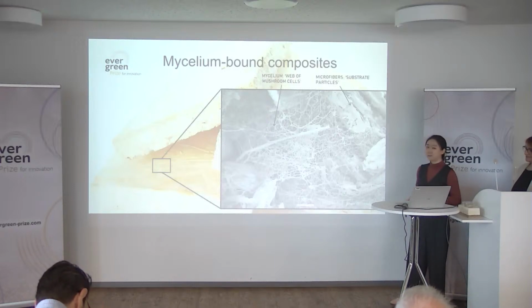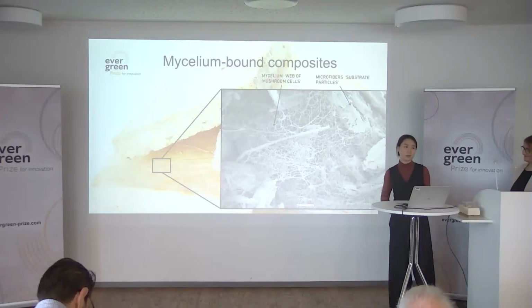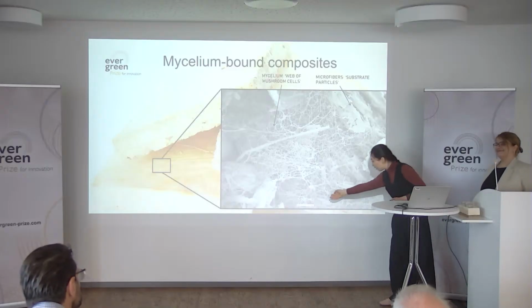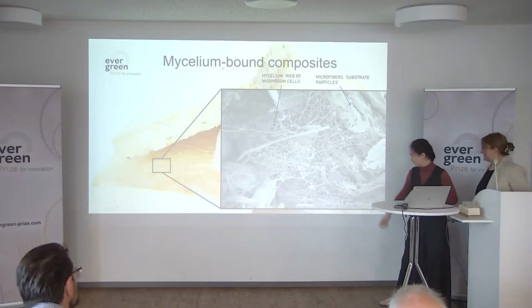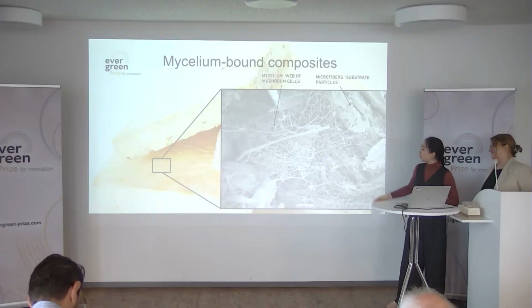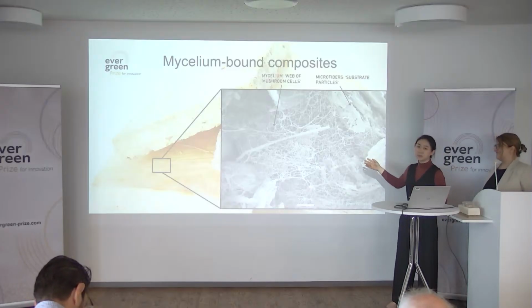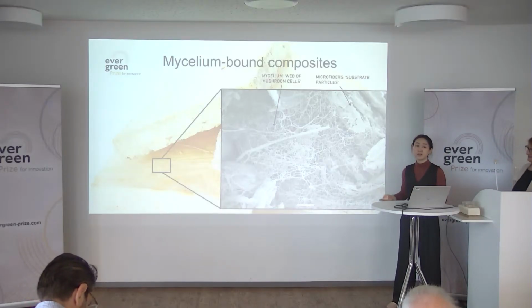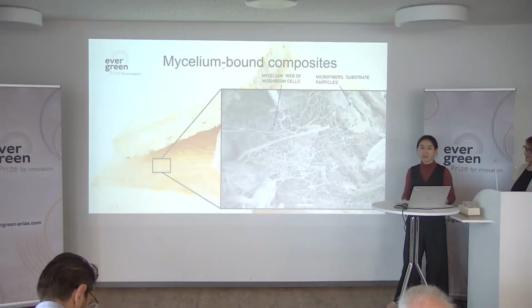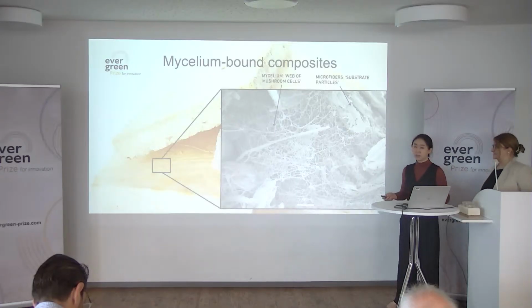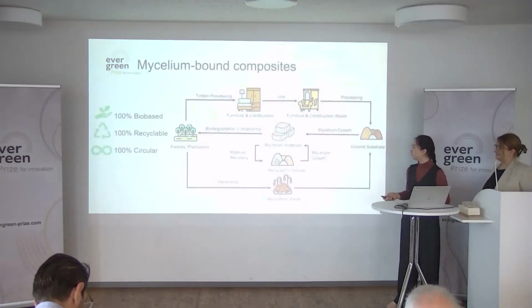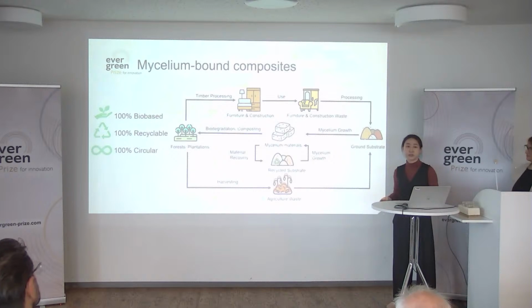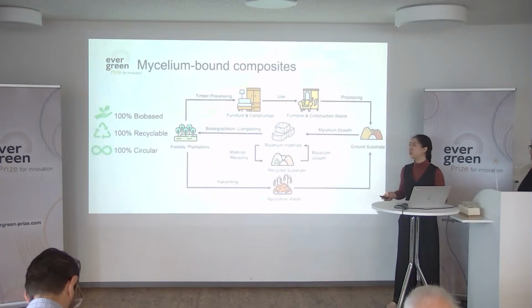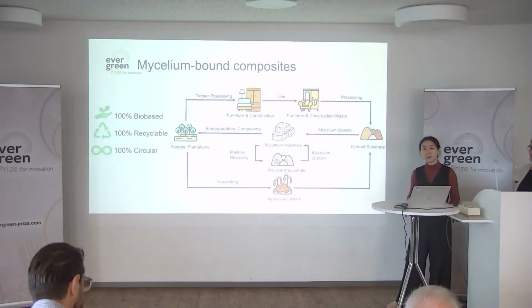And just a fun fact, your hair is about 50 microns thick, which is about half the length of the scale bar over here. Hope you can see it. And you can see that our mycelium fibers are much thinner than the diameter of your hair. And yet they are strong enough to actually bind every single thing together without any additional binders or adhesives. So that is actually pretty amazing by itself. And because there are no additional adhesives, our material is completely bio-based, recyclable, and circular.